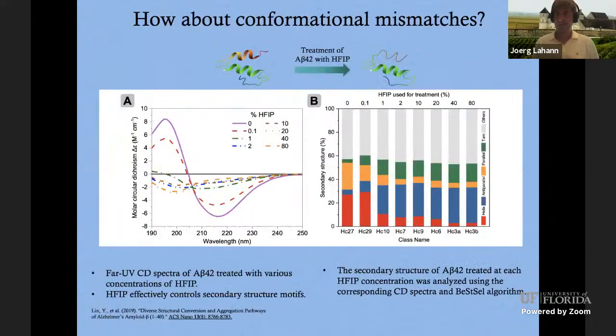Okay, so it works well with sequences. How about conformational changes? That's even harder, right? Because those are potentially a little bit more transient. Now, the nice thing is the field is very well versed in inducing those conformational mismatches. So what you do is you take the peptide and you add a little bit of a solvent called hexafluoroisopropanol. That creates a hydrophobic environment. And then by the amount of this HFIP you add, you can disturb the structure and the alpha helix and beta sheet content systematically as a function of the amount of solvent that you use. And so by doing this, we have access to different conformations of this particular peptide. So the sequence is always the same, but the conformational state changes as a function of the HFIP.